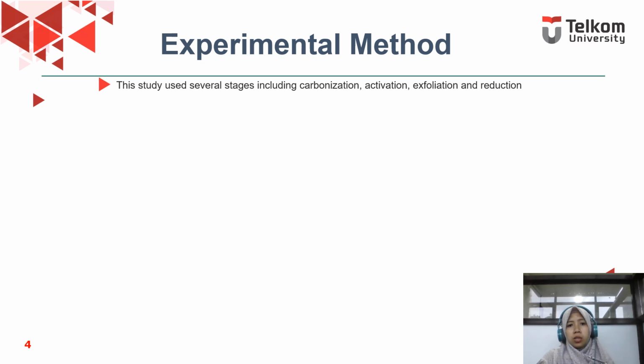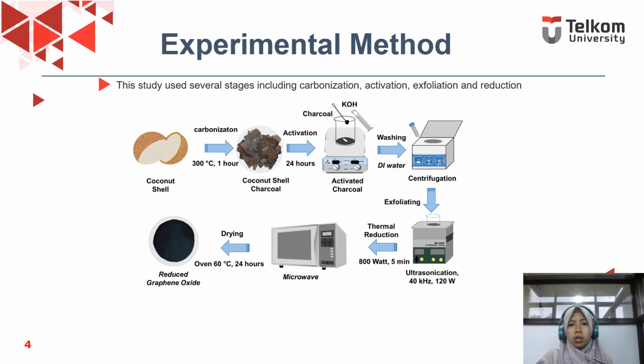The study used several stages including carbonization, activation, exfoliation, and reduction. For the first time, the coconut shell was dried for 1 hour at a temperature of 300 degrees Celsius and then activated for 24 hours using potassium hydroxide as an activation agent. The sample was then washed using DI water and exfoliated using an ultrasonic bath. The last stage is the reduction process to remove oxygen functional groups using a microwave for 5 minutes.